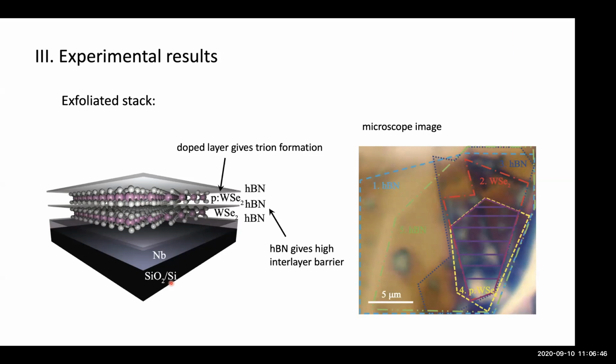Hey, David. I have a question here. In order to create this image charge, you want to put, for example, the tungsten diselenide directly in contact with your metal. But on the other hand, we know that those metal contacts will dramatically change the lifetime of the photo-excited carriers, for example, excitons, right? You're saying the contacts on the sides or the metal that they're sitting on top of? The metal they are sitting on top of. Yes. Well, it will change the binding energy, which will change the oscillator strength. It's not a super dramatic effect on the exciton, but it's a measurable effect on both the trion and the exciton.